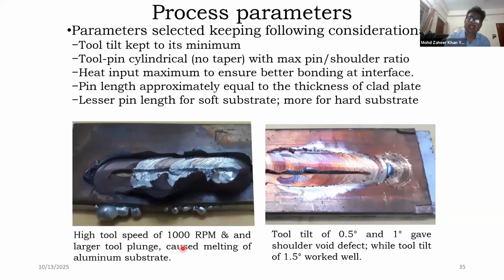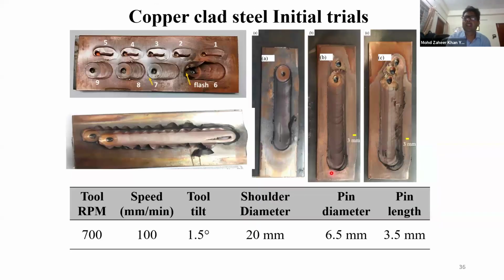So just like any process is difficult, here also we faced a lot of difficulty. If the process parameters were not optimized, in the case of cladding of copper on aluminum, there was melting of the substrate, as you can see over here. And in the case of welding of copper on mild steel, there were defects like shoulder void, excessive flash, and other defects. So after several trial runs at the process parameters listed in the table, we could successfully deposit a layer of copper on top of the mild steel substrate at a tool RPM of 700, at a tool translational speed of 100 millimeters per minute, tool tilt of 1.5 degrees, shoulder diameter 20 millimeters, pin diameter 6.5, and the pin length was kept 3.5 because the thickness of the clad layer that we are trying to deposit was 3 mm.